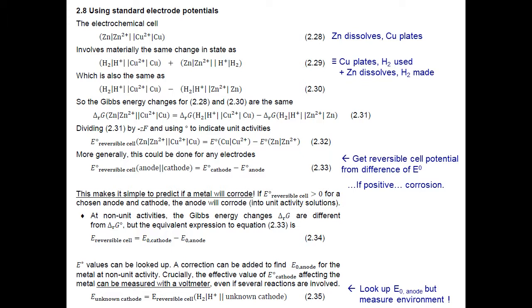The difference between 2.34 and the previous equation 2.33 is that in 2.33 I had superscript circles in the algebra indicating unit activity, and in 2.34 I have subscript zeros next to my E terms, which represent equilibrium but not necessarily at unit activity. So it will turn out we can get this simple expression for what is the reversible cell potential of some process, and it's just the difference between the standard electrode potential of the cathode and the anode.